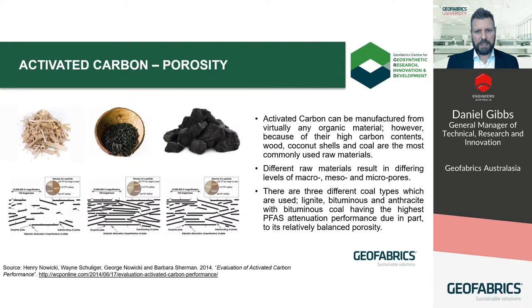Activated carbon made from wood generally has a larger number of macropores, while coconut shell-based activated carbon has a higher level of micropores. Coal is somewhere in between these two with a reasonably balanced porosity, having similar levels of each pore size. And this is an important distinction in the context of having a product which has the correct size and number of pathways required to maximize PFAS adsorption. A further distinction is the type of coal used. Research by others has shown a higher PFAS attenuation capacity using bituminous coal over the younger lignite or older anthracite types.